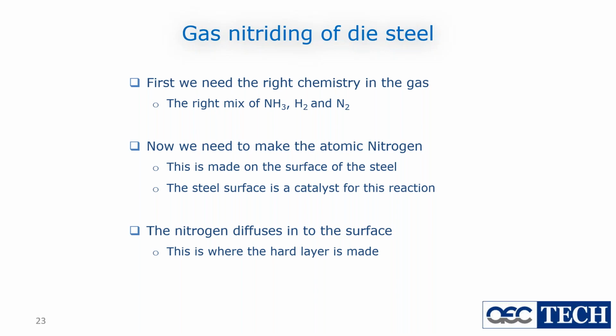The number one most important thing I want you to remember from this presentation is that the reaction occurs on the surface of the steel, very, very, very close to the surface, fractions of a thou from the surface. The reaction occurs, the ammonia, the nitrogen, and the hydrogen all touch the steel, and at that point, atomic nitrogen is made. And some of it diffuses into the steel, and that's good.